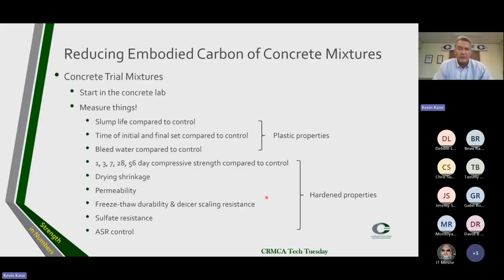They would actually do some wall placements where they would order a pump. The pump would come in, pour the first lift. The pump would leave, and another pump would come back 4 hours later to do the second lift. That's how difficult that mix was to work with. But we wouldn't have known that if I hadn't measured the time of the initial set.